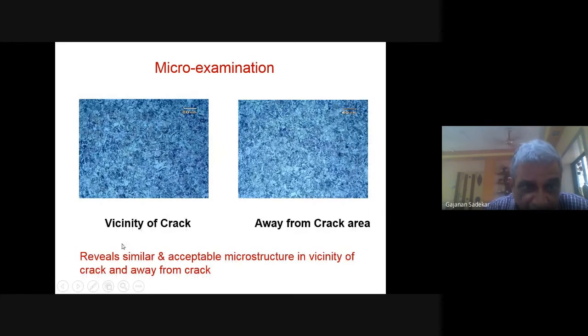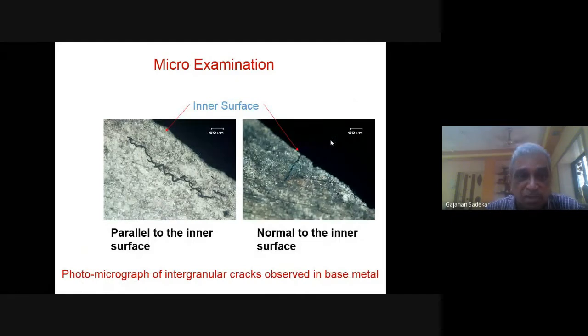Micro examination again reveals similar and acceptable microstructure in the vicinity of the crack, near the crack and away from the crack area. In the vicinity of the crack, microstructure was okay, and away from the crack also microstructure was okay. But what happened in the other area we'll see. Now look at this particular thing, where the cracks have occurred parallel to the inner surface. Photograph of intergranular cracks observed in the base metal. They are intergranular cracks. Okay, that was a very important thing to note.